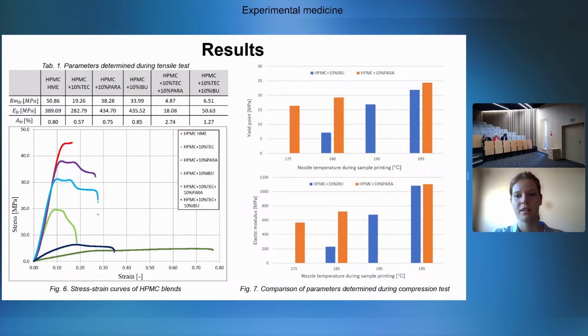The tensile strength test was used to measure 3 parameters: tensile strength, elastic modulus, and elongation at break, which is presented here as relative to the length of the sample before the test. Pure HPMC was noted to have the highest strength of all samples. Based on obtained results, both API and plasticizer noticeably affected mechanical properties of the material. Ibuprofen and paracetamol both acted as a plasticizer for HPMC, lowering durability of the material while increasing its ductility.